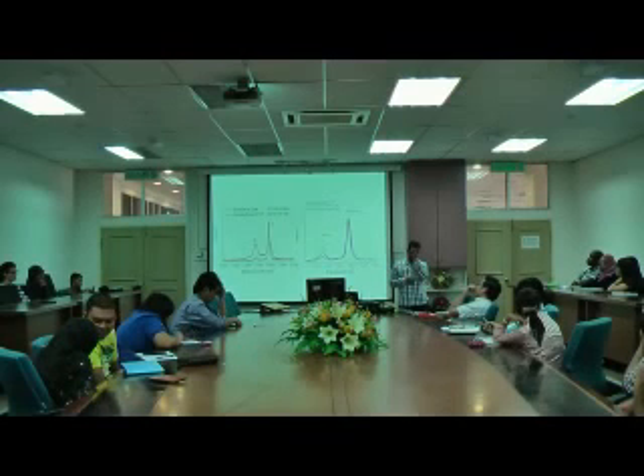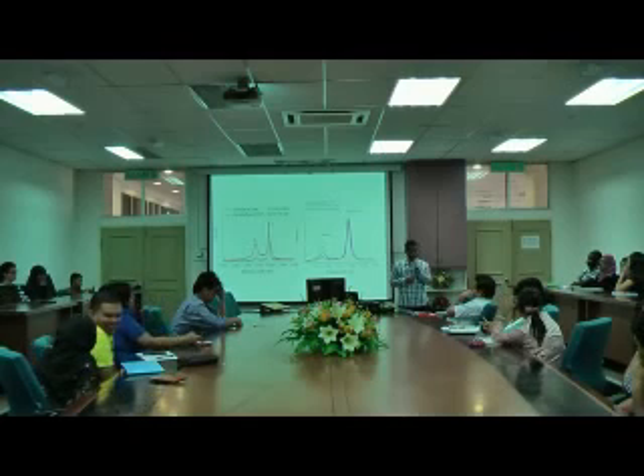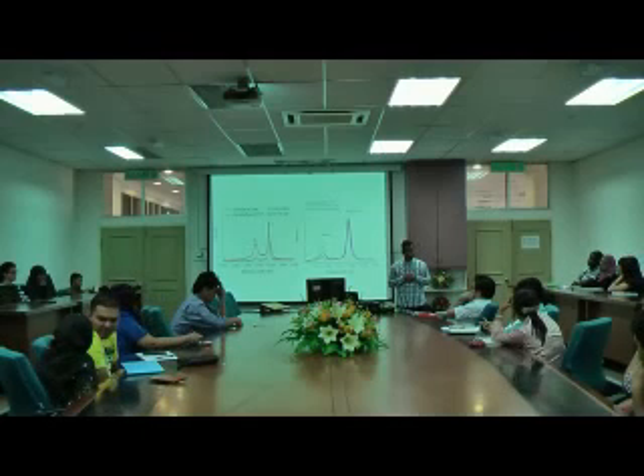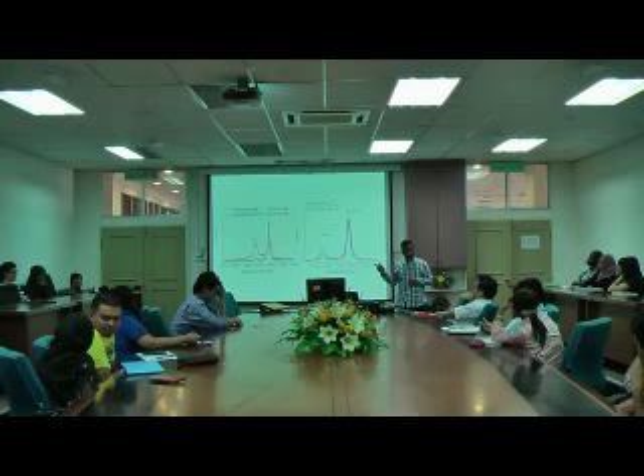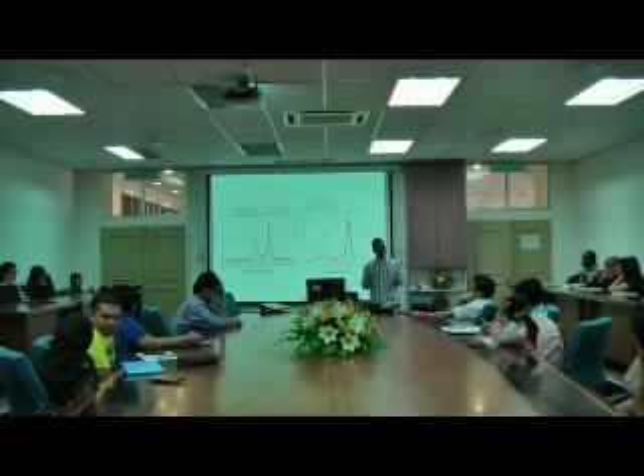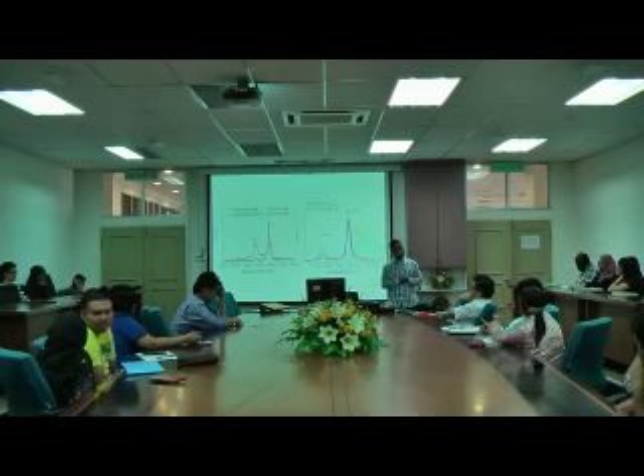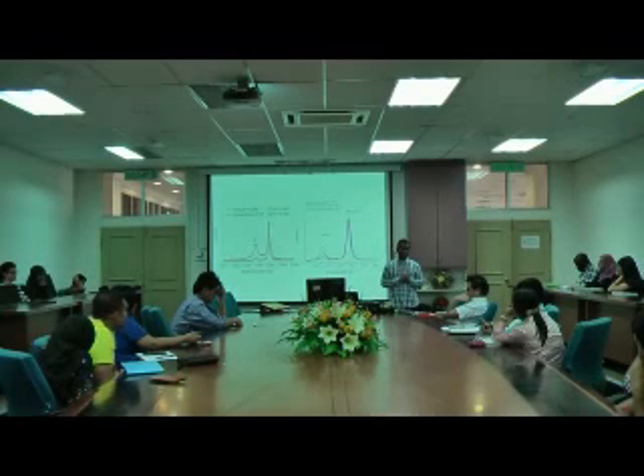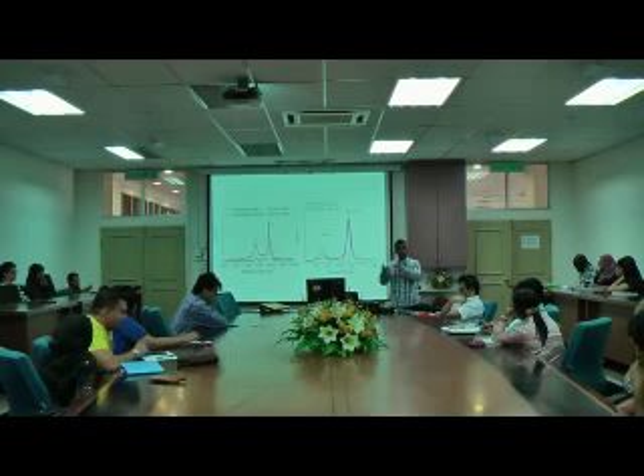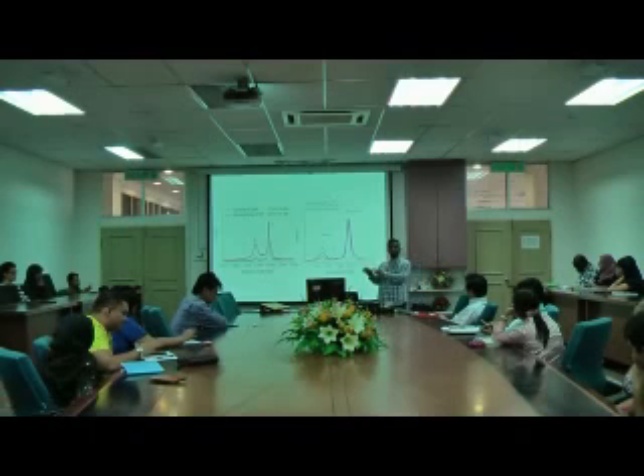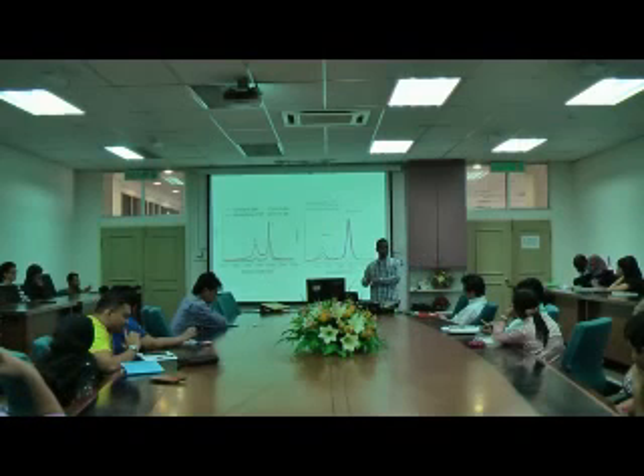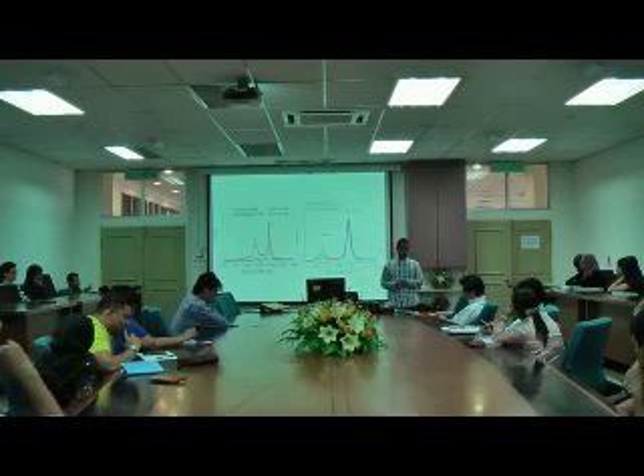If you look at the graphene we use in graphene synthesis, the Raman spectrum of that reduced graphene material is actually similar to carbon black. It's oxidized too much, with too many functional groups. So as I said earlier, in our experimental plan, we want to simplify the system. We don't want to complicate it because we will find problems in interpreting the data, or a reviewer will argue that this is not the case, blah blah blah.